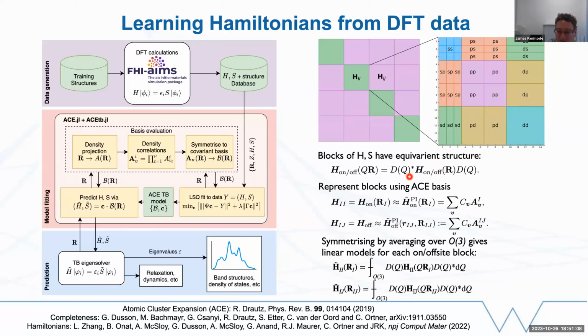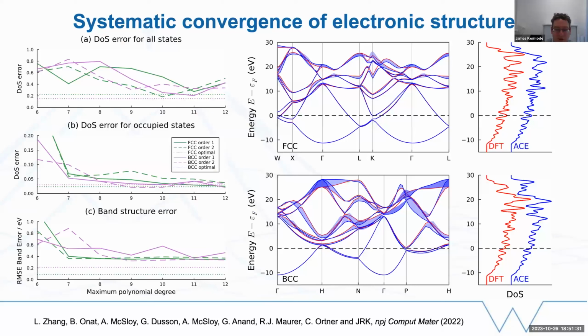Still uses atomic environments to describe them, but the target values rather than energies and forces are now blocks of the Hamiltonian matrix. And we can use a similar setup to make predictions for on-site and off-site blocks of the Hamiltonian. And from that we can get, let me skip just to show one result from that. From that we can get very nice predictions of electronic structure. So now we're getting access to electronic quantities directly from these data-driven models, rather than just energies and forces like we have in interatomic potentials.